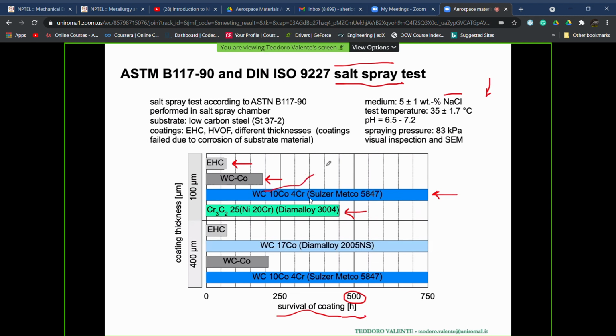See here, we have 86% of tungsten carbide, 10% of cobalt, 4% of chromium. And I think we do not need to add anything, because just having a look, depending obviously on the coating thickness and on the length of the bar, we can see how, in this case, with respect to corrosion resistance, we have different properties depending on the material selected for the HVOF. But we can reach very performing results if referred to the behavior of components treated on the surface with electrolytic hard chromium.